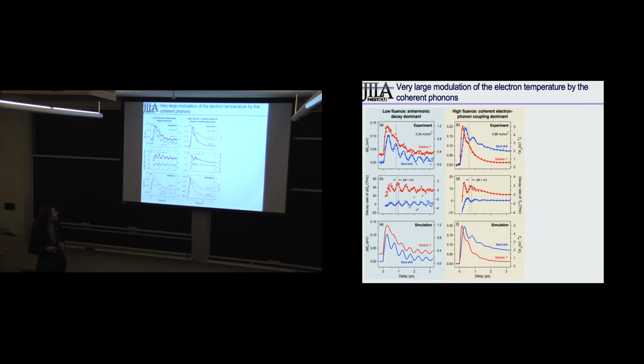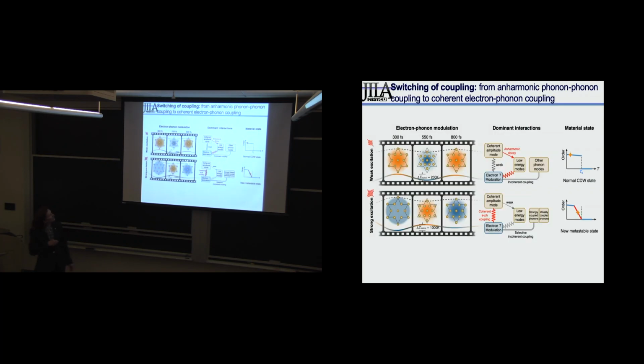And in this material, we think actually there's just many, even though we can't confirm this without a RIXS measurement or something, which is why I'm trying to mention it, we think that at weak excitation, the coherent amplitude mode decays by anharmonic decay, and then that couples to the electrons, whereas at strong excitation, in this metastable state, the coherent amplitude mode is relaxing by modulation of the electron temperature. There's all of these other phonon modes also involved, so it would be a really neat experiment to see if we could test it. This is what we think the RIXS data is telling us, but it has to be tested.